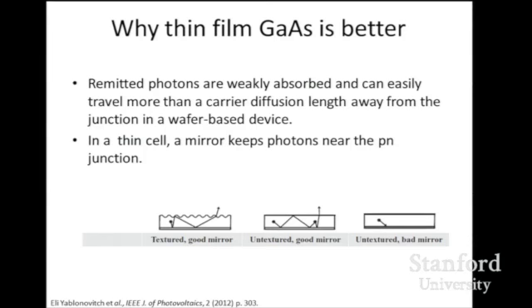Now, if you have a thick wafer, the photon could go deep down into the wafer and generate carriers far away from the p-n junction. And then you might lose those carriers. But if you have a thin cell and a good mirror, then you can really keep those photons trapped up near the p-n junction, and you can just recycle those photons and put them to good use. And that resulted in the world record efficiency of, I believe, 28.8%, which is the record for a single junction solar cell.